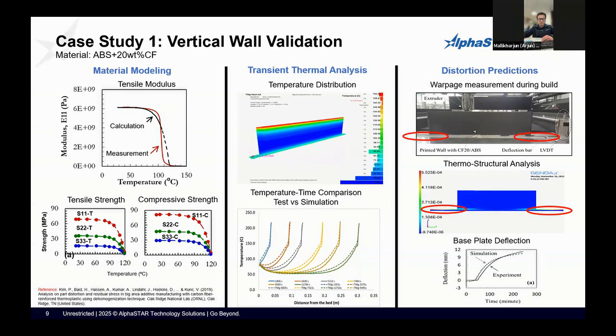So on the middle pillar, we can see that we simulated the temperature, and on the bottom, that's the validation. The dark lines are the temperature that's captured from the simulation, whereas the dotted lines are predicted from the thermal analysis. Once we have thermal completed, validation complete, we take the thermal to a mechanical where we solve for stresses, displacement, warpage, and also damages.